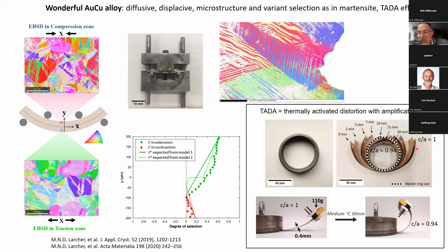Then we do nothing. We just put this thin foil again, without any stress, into the furnace. And without any applied stress, by itself, it continues to roll on itself. Why is it like that? It is because we have formed martensite nearly everywhere, but with a very low c/a ratio, very close to 1. And when we continue the transformation, since the variants are already there, even if there is no force, they continue to grow, and we continue to see the distortion macroscopically. It's very surprising, but you can even generate a force by that.